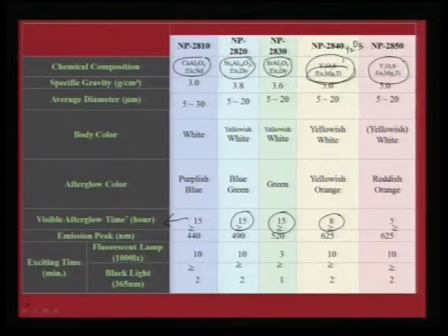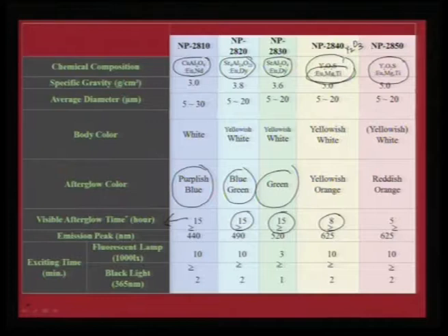So, depending on the constituents, they form a different story in terms of light output. As you would see, calcium aluminate with europium is very selective for purplish blue, strontium aluminates for blue and bluish green, and then strontium aluminate, the lower analog with europium, is specially meant for green fluorescence.